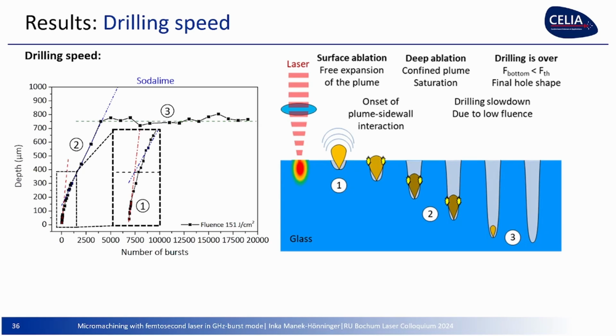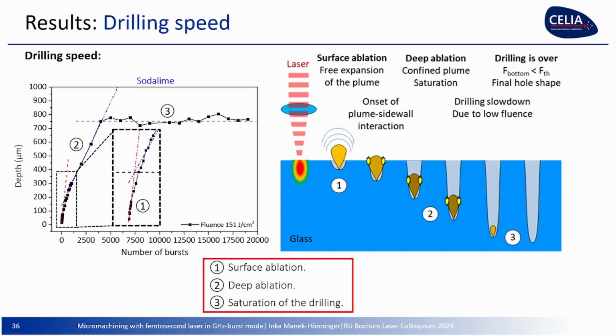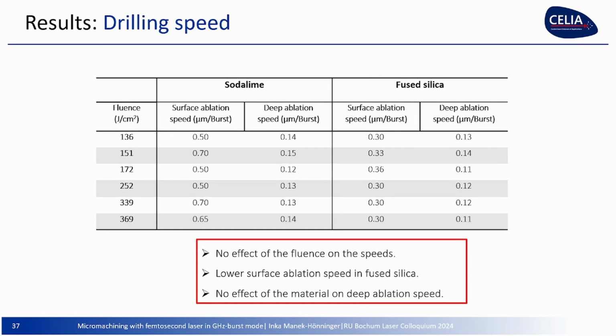Why? How can the laser beam go down there? Of course, it's internal reflections within the hole. But at each reflection, of course, you have some refraction losses, you have some diffusion losses, scattering losses. And so the energy is diminishing, and when there's not enough energy left to drill, then drilling stops, and drilling is over. So we have surface ablation, deep ablation, and then the saturation of the drilling, and there's no energy left.